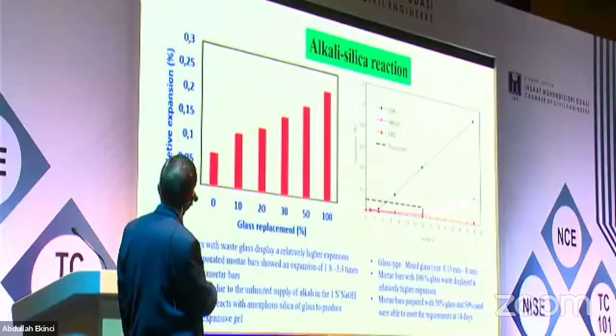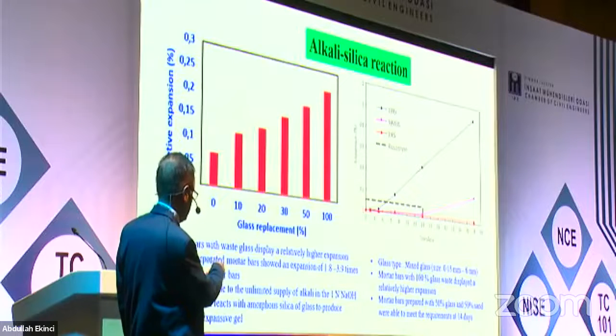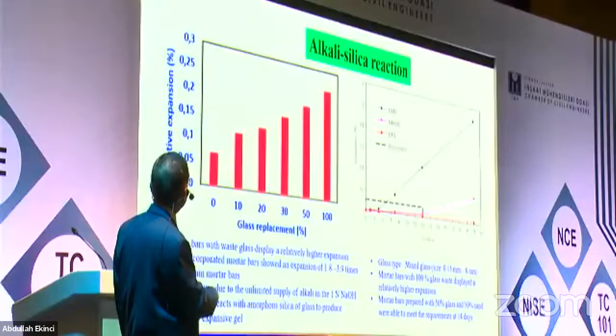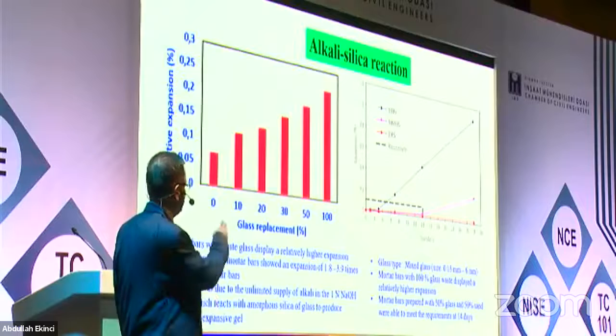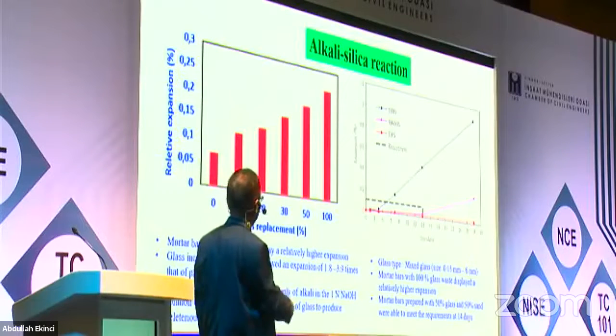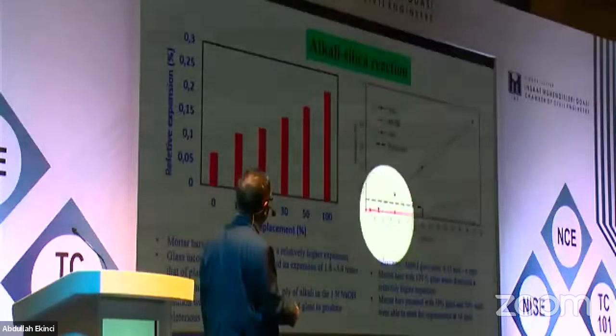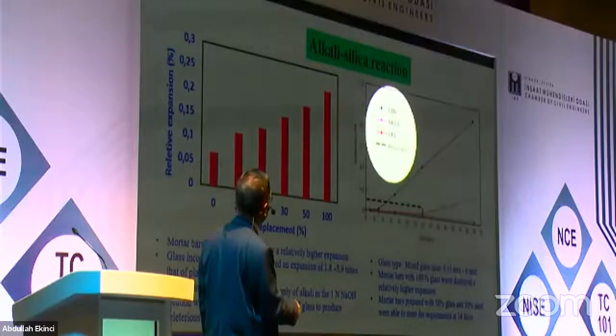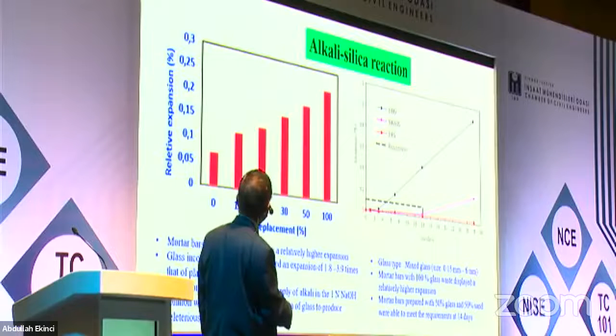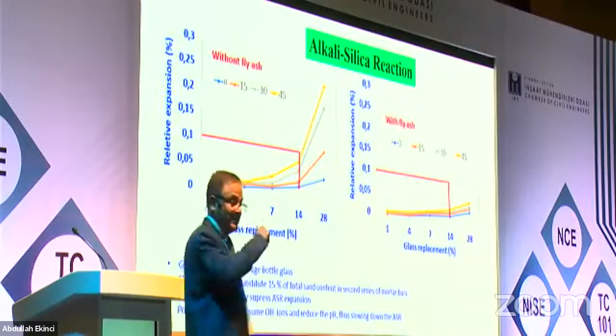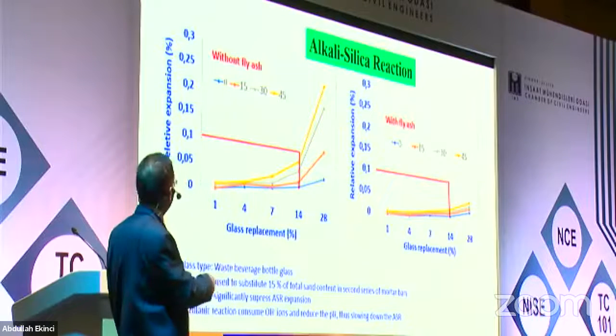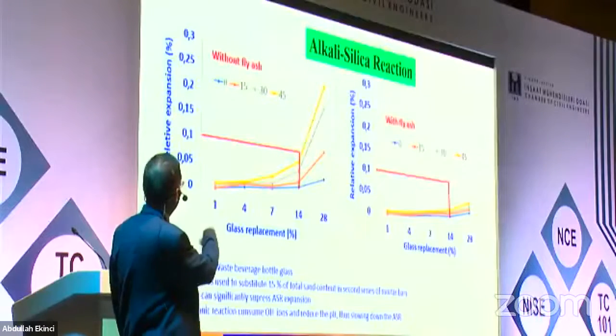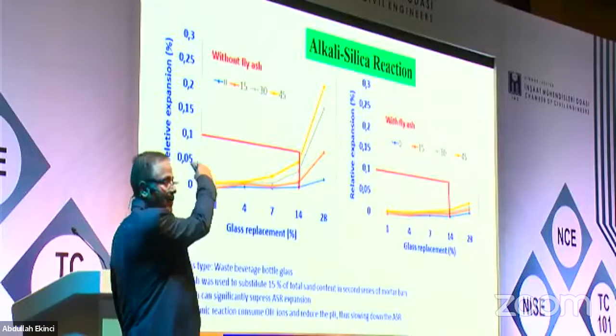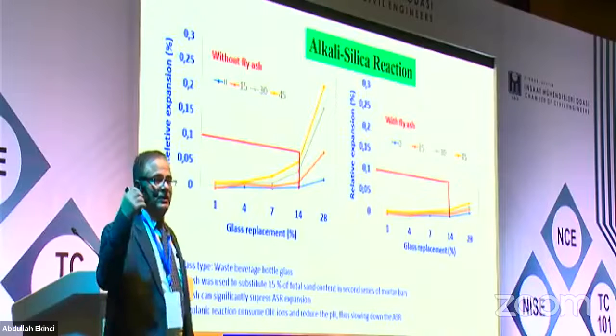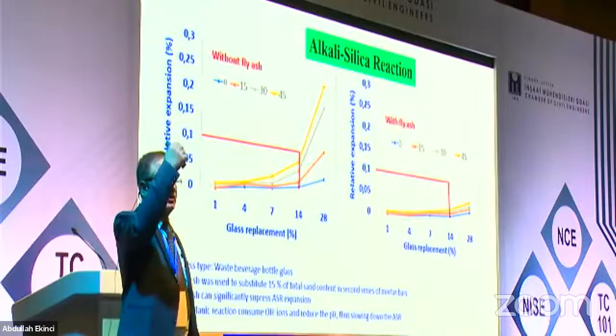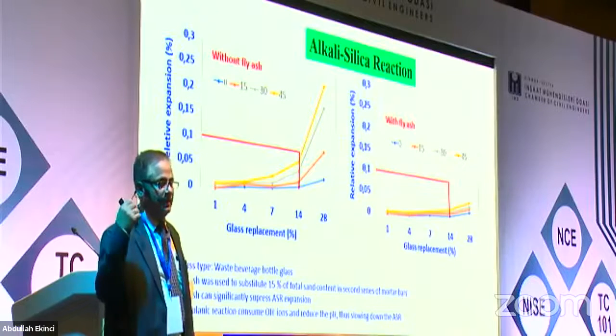Look at this. Relative expansion. See here, look at this. The permissible limit is 0.1, and then for 100% you got this. See this. This is a solution with supplementary cementing material. Look at this graph. Without fly ash, you have high expansion. With fly ash, all within the range. Similarly, if you use fly ash, silica fume, metakaolin or rice husk ash, you can control the alkali aggregate expansion, the alkali silica reaction.